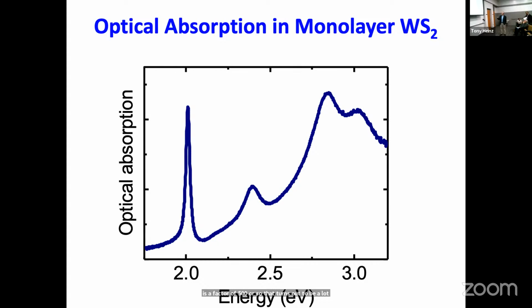So we understood that this thing is clearly a signature of having a very strong excitonic interaction, much more pronounced than you typically see in semiconductors. The excitonic effects are well understood, but they're usually predominant at low temperatures. So we understood early on that was a hallmark of strong excitonic interactions.